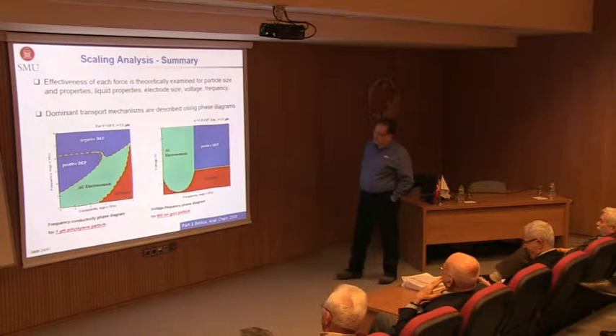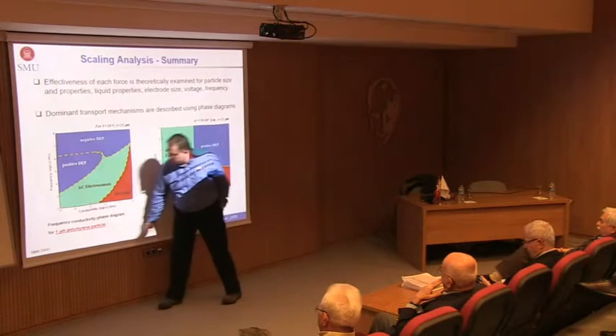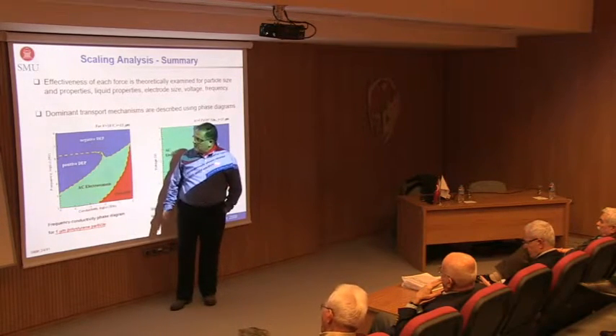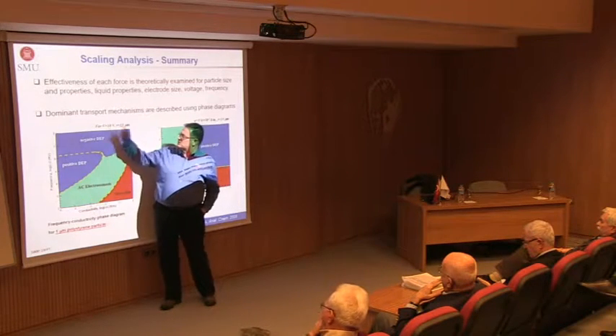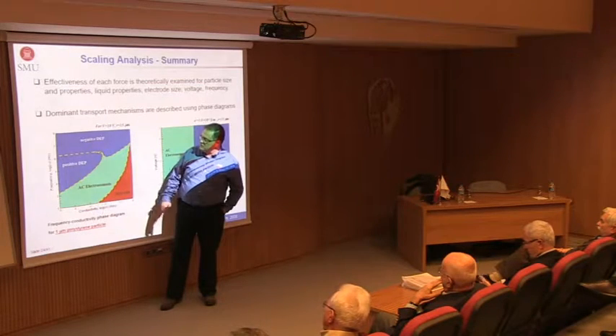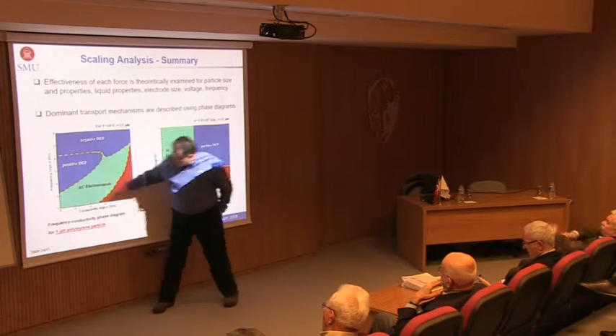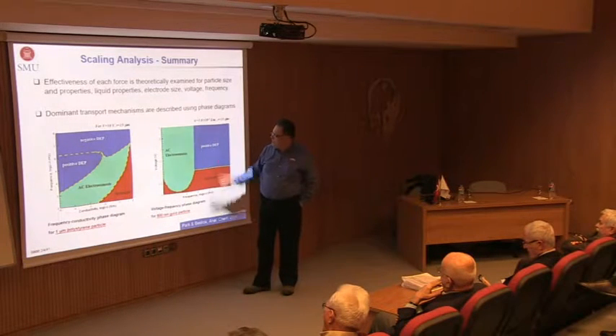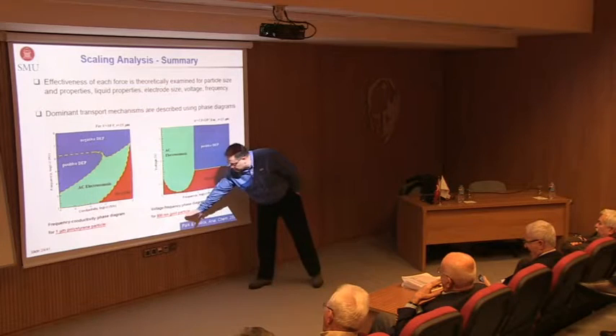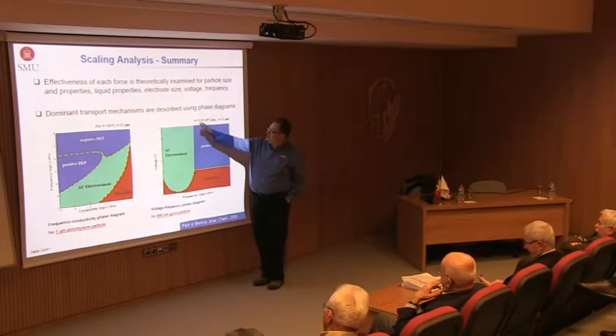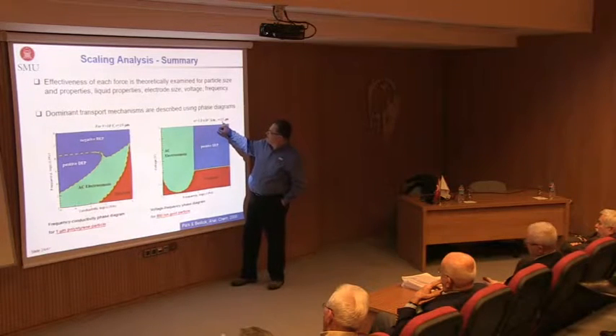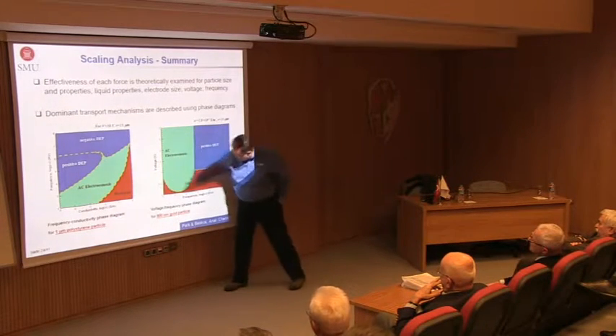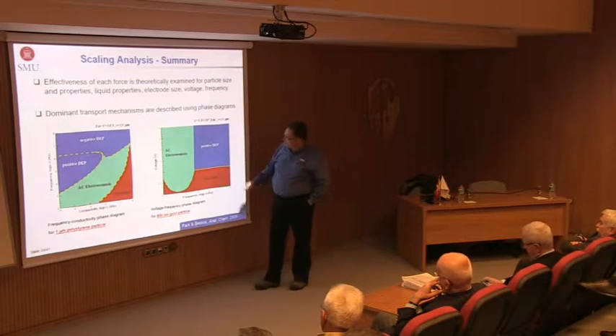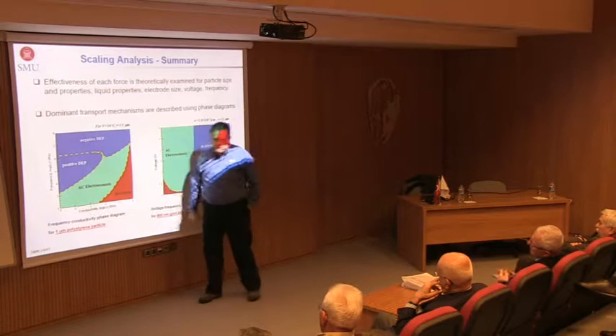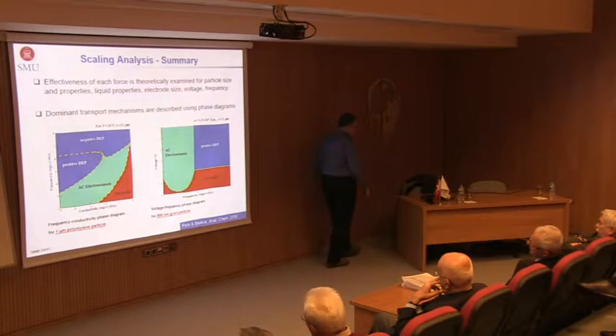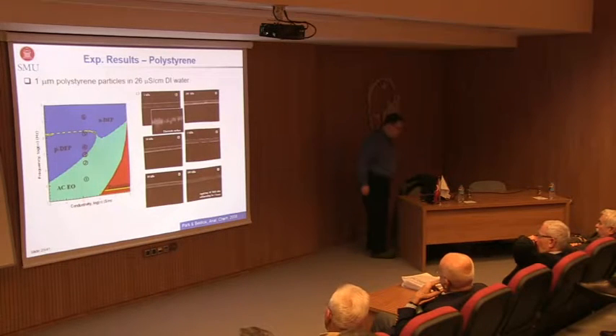So let's assume that, say, we have 1 micron polystyrene particle. If I know the particle, I know its sigma and epsilon. Those are all determined. And if I know the applied voltage that I would like to use and the electrode spacing, I can come up with frequency versus conductivity phase diagram. Or if I have, basically, gold, now I know this particle and its properties. If I pick the ionic conductivity of the fluid and the electrode design, I can actually have voltage versus frequency diagram. And these are basically the maps that we generate to try to understand what we expect in any experiment that we do. I'm just going to show one of them for you.